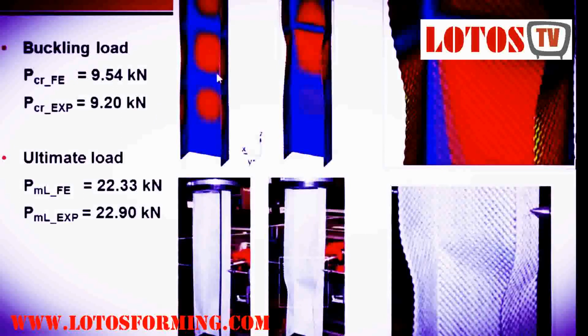We also look at the numbers, the buckling loads and the ultimate load. The buckling load of the simulation also compares very well to the experimental result, as well as the ultimate load, with a very small percentage difference between the two values. So this again confirms that the approach we propose in this case is reliable and accurate.